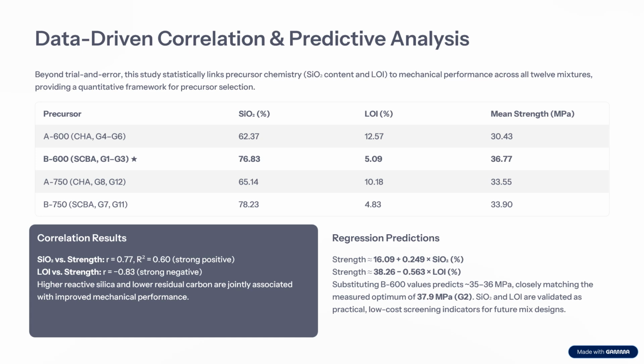As for the data-driven correlation and predictive analysis beyond trial and error, this study links precursor chemistry, the SiO2 content and the loss on ignition level, to mechanical performance across the 12 mixtures, providing a quantitative framework for precursor selection. For precursor selection, we prefer B600 SCBA from G1 to G3, which has silica 76%, LOI 5%, and mean strength around 36.77. However, when we have higher silica, the mean strength was reduced to 33. For the low value of silica, we have the lowest mean strength, around 30.4.